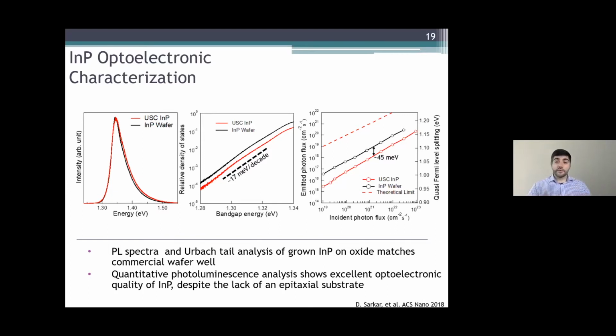We're comparing the Urbach tail parameter, which essentially gives you a sense of the disorder of the material. And finally, the quantitative photoluminescence, which tells you something about the relative rates of non-radiative recombination in the material. And what we see is that while it's not exactly the same, it's actually pretty close to a lot of these single crystalline wafers that you can buy.